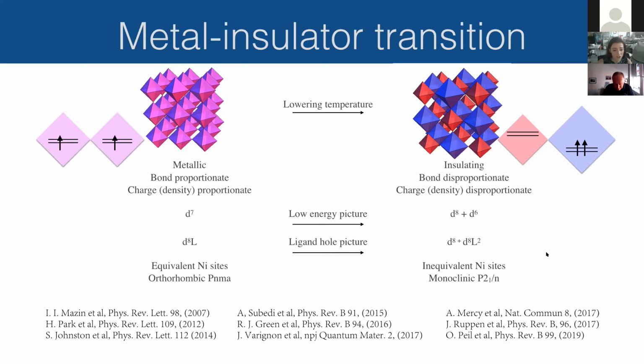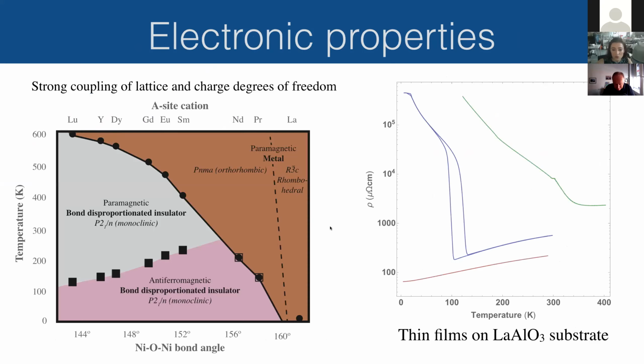Now, this transition has been studied a great deal. This is just a small selection of the theoretical papers and computational works that have addressed this transition. Just to show you some experimental data now of what the transition really looks like. Here I'm just plotting 3 different nickelates, and they are lanthanum nickelate, which is the one with the largest cation. It has the straightest nickel-oxygen-nickel bond. And corresponding to this, it turns out that it's metallic. So that's why you don't see a transition along this line. Next up here is neodymium nickelate, which is a bit more distorted. So this one does become insulating.